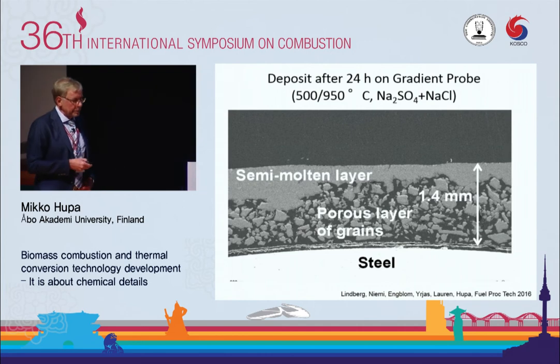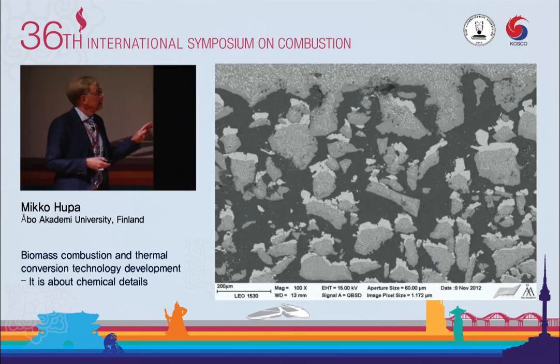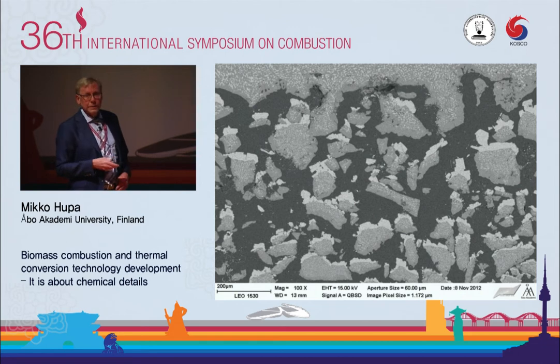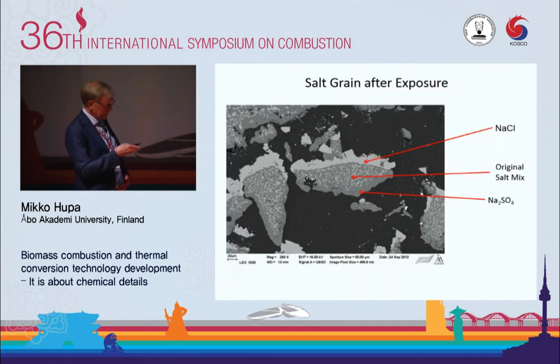But if we take a closer look into this, we start seeing that also the type of the particles have changed. The particles didn't look like this when we put them in. So now they have this white layer on top. And if we take one more close-up, we can see that, yes, each particle has received this white layer of material. And also the lower part looks different. Now, the center of this particle shows how they looked before at the beginning, original salt mix.